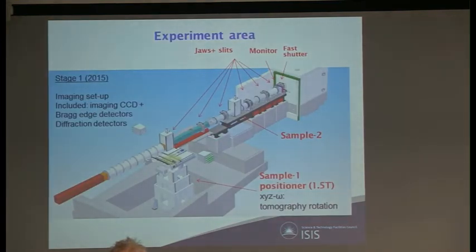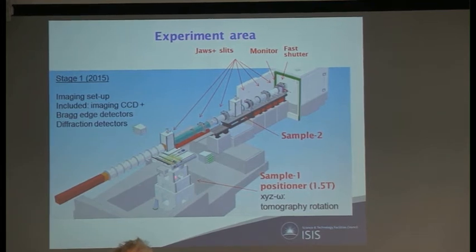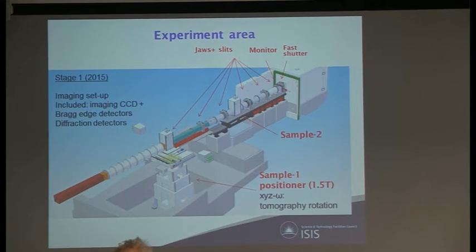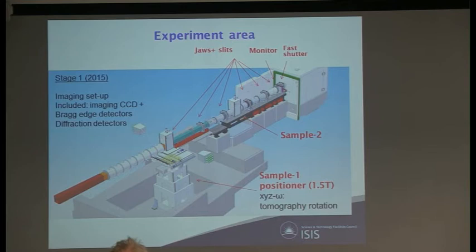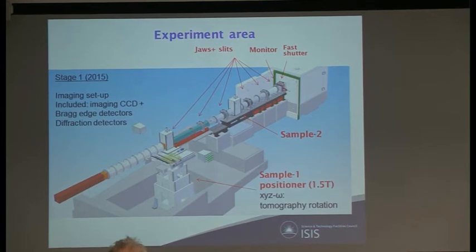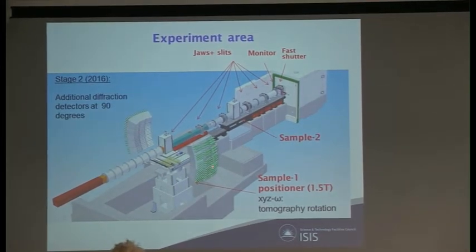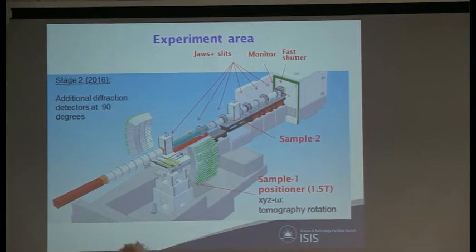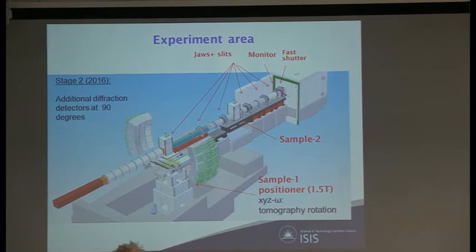Okay, so here again the main components in the experimental area. The main point here is that we will have a heavy-duty sample positioning system, which can move samples up to 1.5 tons, and then the cameras. Initially, and also next year, we will have a selection of cameras and a small number of diffraction detectors. And in the second phase, a year later, we will build up detector arrays, first at 90 degrees and then later also at other angles to do the diffraction scans. To give you scale, the size of this camera is 1 meter in height.